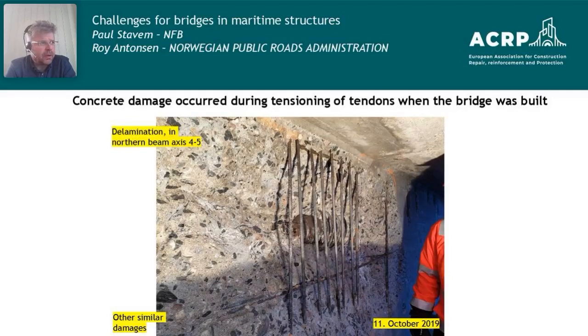And it's very normal that we find delamination on coastal bridges in Norway, very normal because of macrocell corrosion, right? But what happened here we never saw before. It's like 100 kilos of concrete that just fell out from one of the beams in the bridge, revealing this steel box here, which is actually the anchors of the post-tension tendons, and they are jointed inside of this steel box.